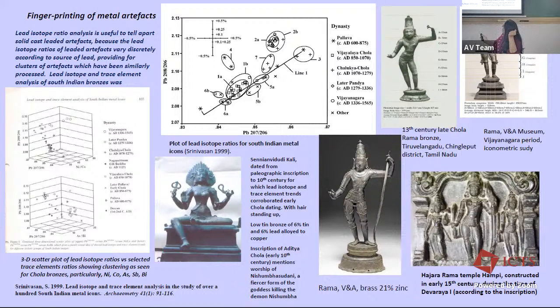And you can see that there's a marked difference from the profiles for the Vijayanagara period bronze. This is a Rama of the Vijayanagara period, and that typically fitted this ellipse up there. So it had very different metallurgical profiles, and here you see him with a bow. This image had quite a lot of zinc in it, 21% zinc, a brass image. So it did seem that more of the brasses were coming later, though there were some exceptional early brasses as well. And you can see here also this typical depiction in the Hazara Rama temple in Hampi of the 15th century, of Devaraya's time, where you show Rama prominently with a bow.